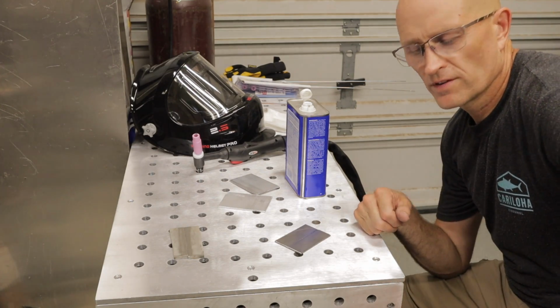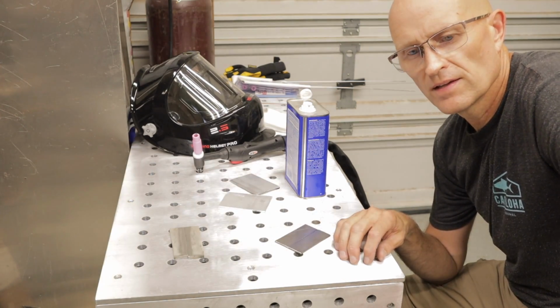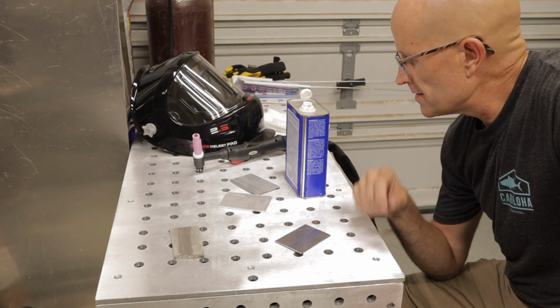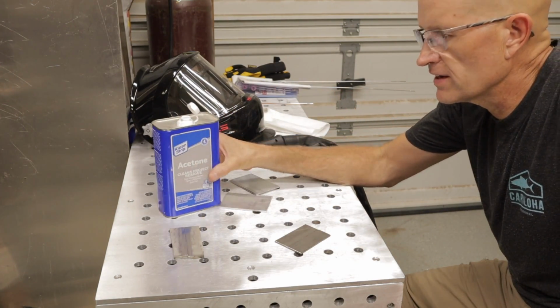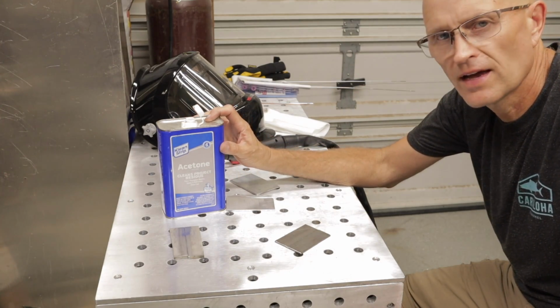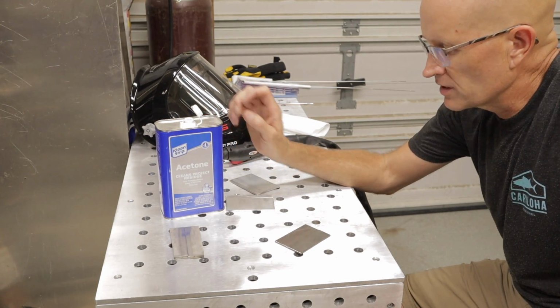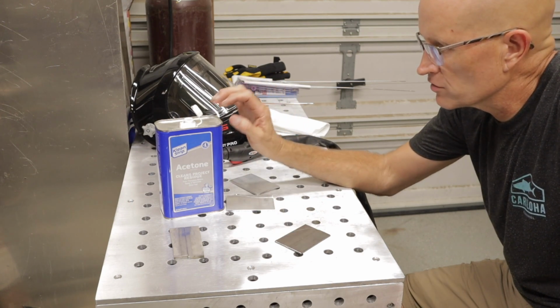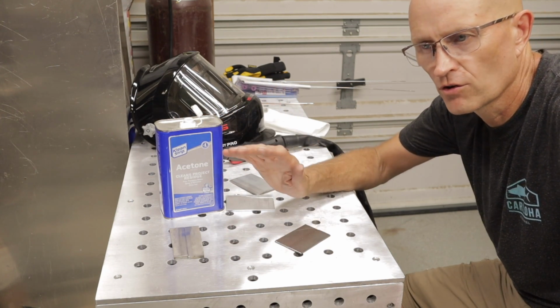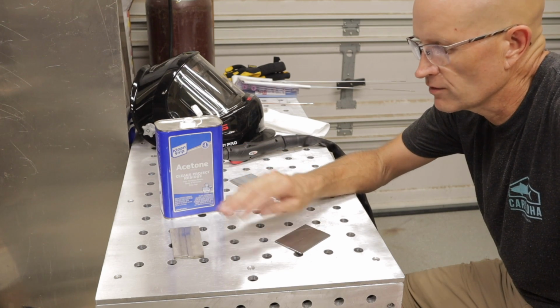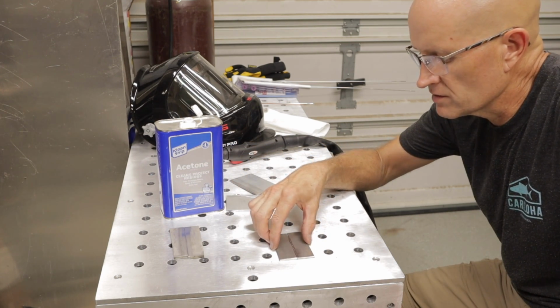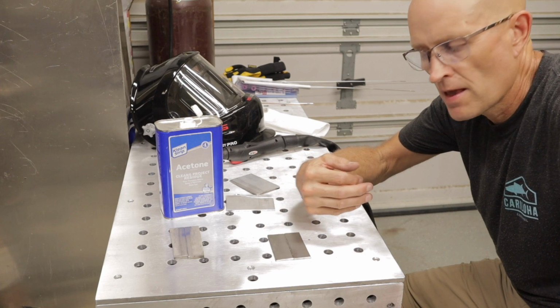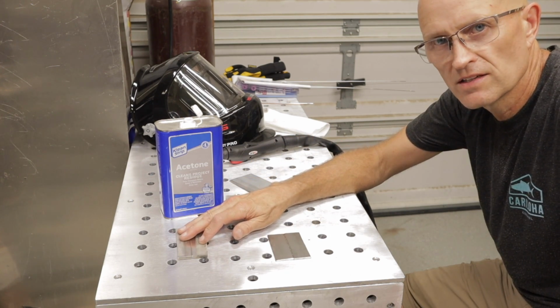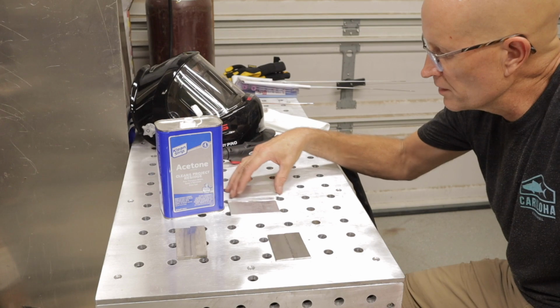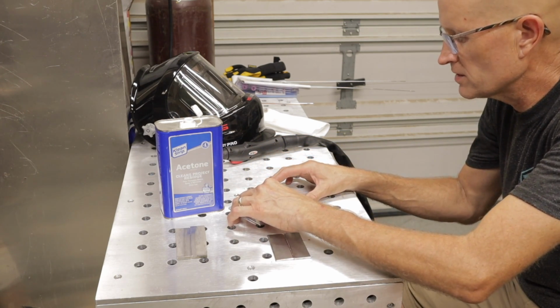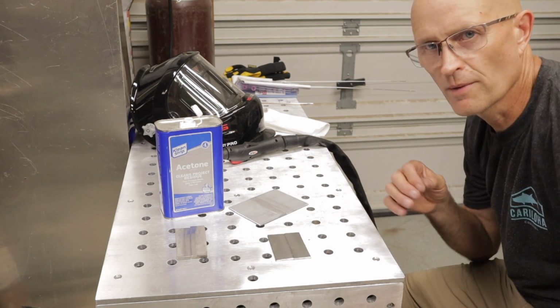Alright, one of the most important things with TIG welding is cleanliness. One of the things you want to invest in is a bottle of acetone. I generally clean everything down to bare metal, and then I also wipe it down with acetone to make sure I get all grease, all oil, any contaminants out of the weld, because TIG welding is not that difficult, especially for mild steel and stainless. But for aluminum, you basically have to be spotless for it to come out nice.